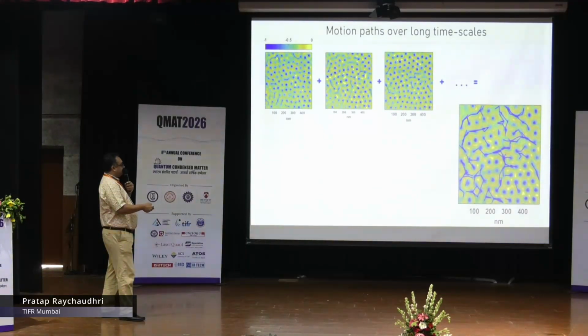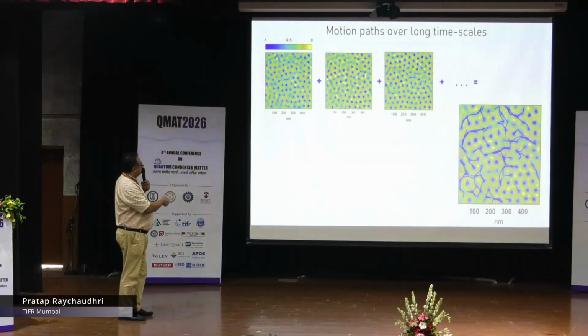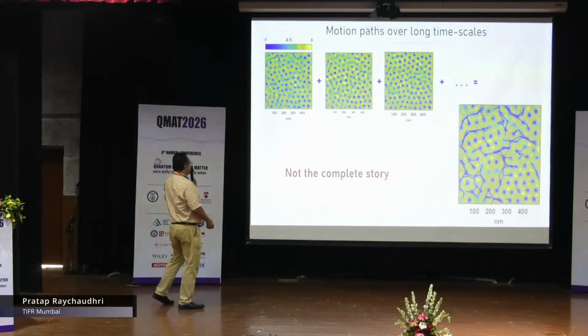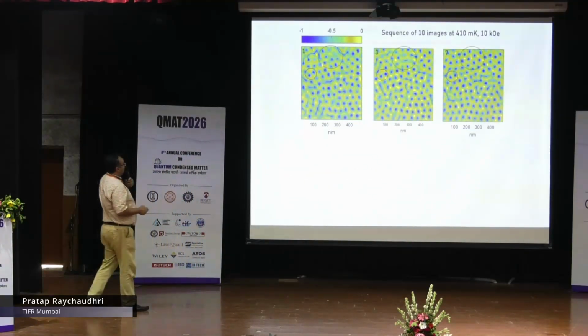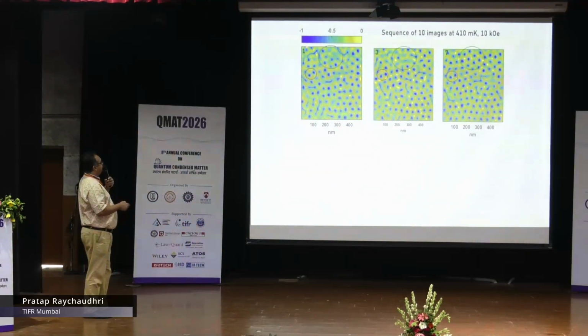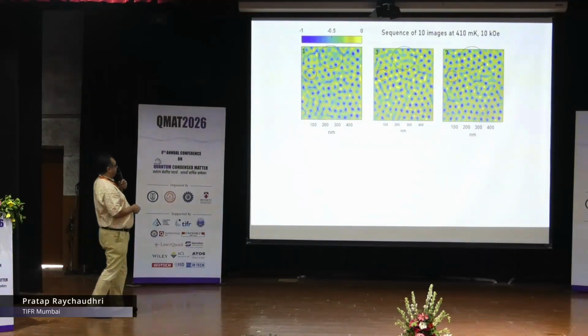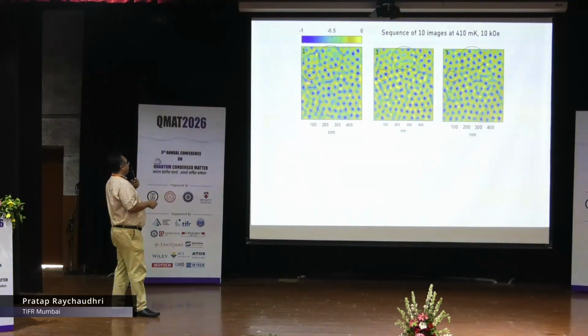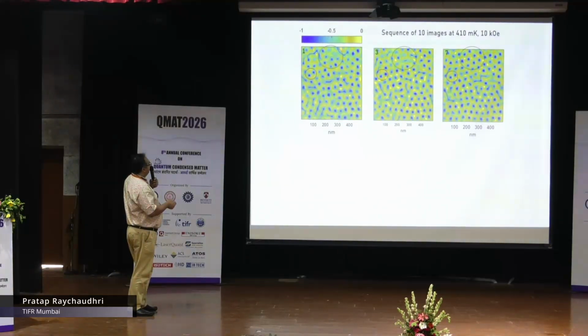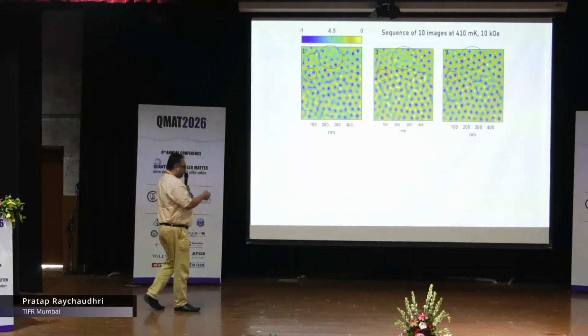So over long scale, the motion path will be given by the sum of all these motion paths, which is shown here. But there is something else. When you look at these images, this is, for example, first, third, and seventh frame of a sequence of images, you see some of these vortices are static and they correspond to deep minima. But the shallow minima here, they not only change position, they also change intensity from frame to frame.